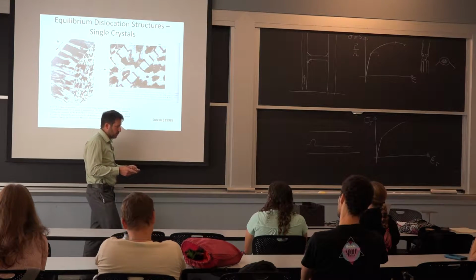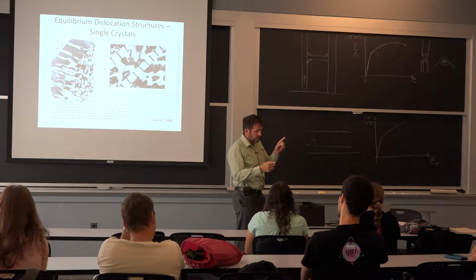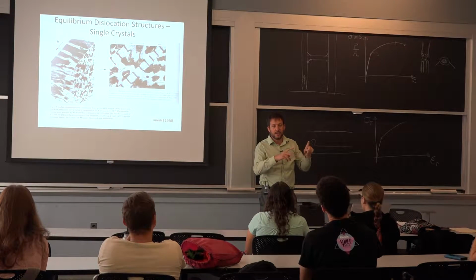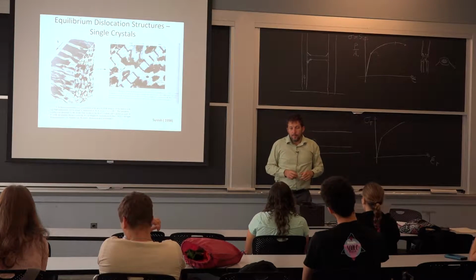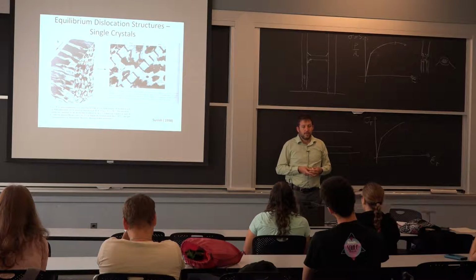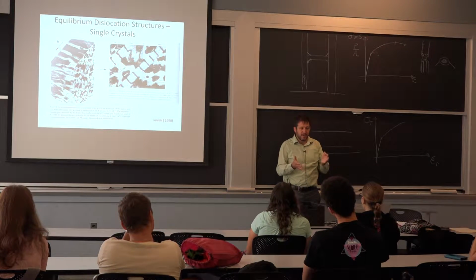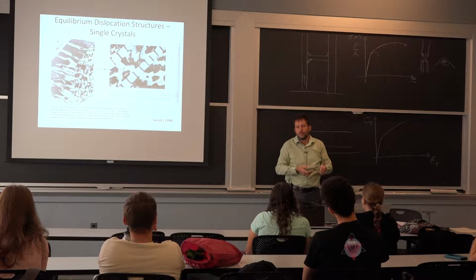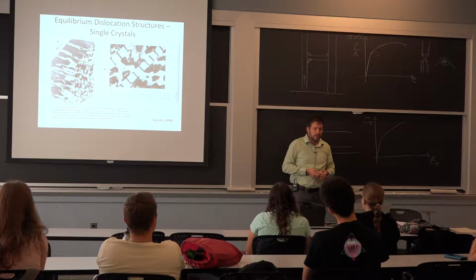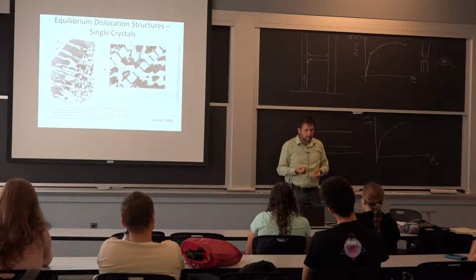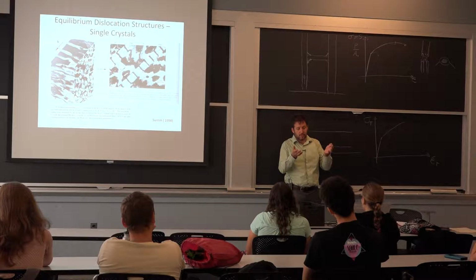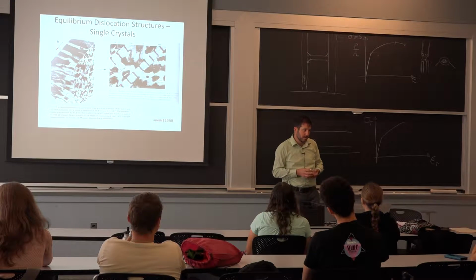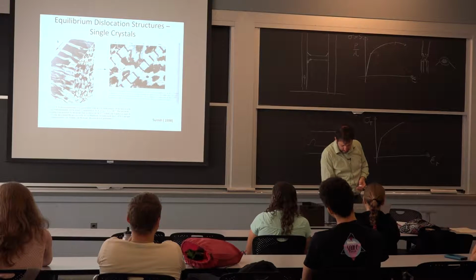So the recovery is where you take two dislocations of opposite sign, they come back together, and there's nothing left. It happens even at ambient temperature at these very, very high strains, but it's because there are so many dislocations, they get so close that they do interact with each other. Now, we will talk in deformation processing about the fact that as you keep increasing the temperature, it is easier for this recombination to take place, and that's called recovery. Anything on the dislocations?